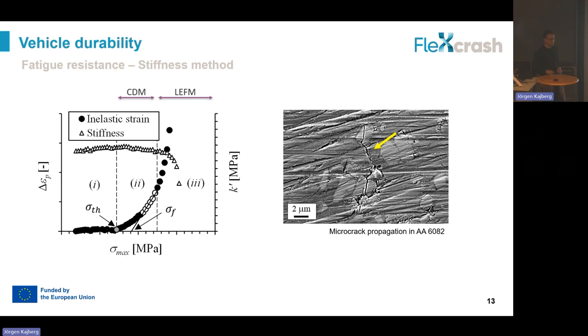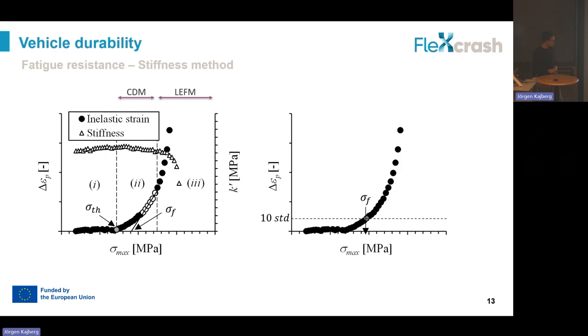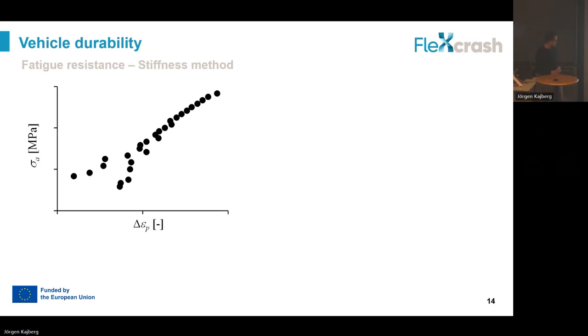fatigue threshold. So the point where we start, or the stress level when we detect that something is happening in the material, and then also the fatigue limit. It can be a little bit different. This depends on the material, and so the damage tolerance of the material. This is one approach, but we can also use another approach where we are defining the fatigue limit, since the first point that reaches the threshold, define it as 10 times the standard deviation of the first point. So this is just a tool to rapidly assess this fatigue limit value.